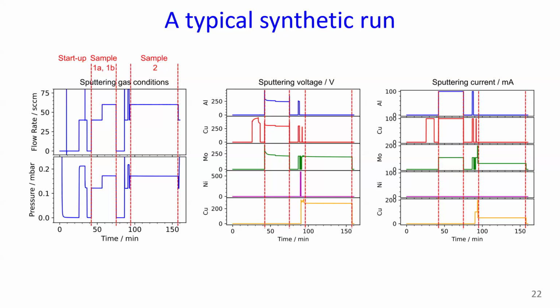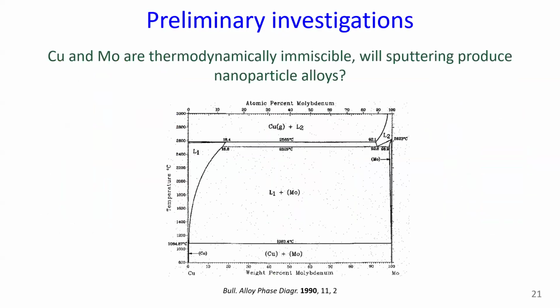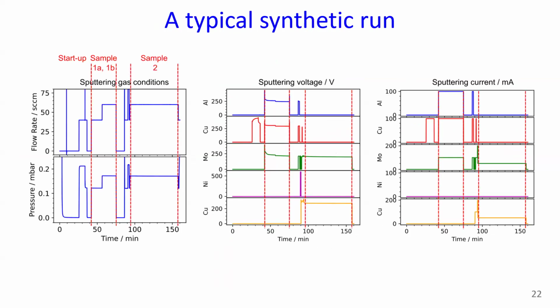When you do the sputtering, are you sputtering the 5 samples at the same time, or just one? Yeah, at the same time. So these are the different targets. Over here we have 5 targets loaded. For this example I'm interested in a copper moly alloy. And so I'm running current on the copper and current on the aluminum. On the moly here, I'm also using aluminum. Sample 2 is without aluminum. And so just by varying the current on the targets, it's continuous and simultaneous.